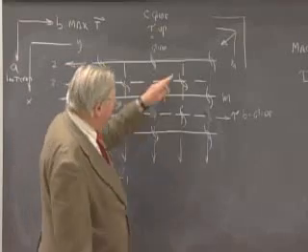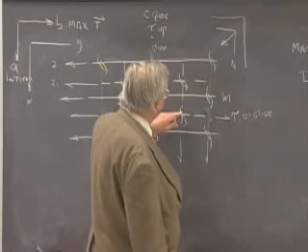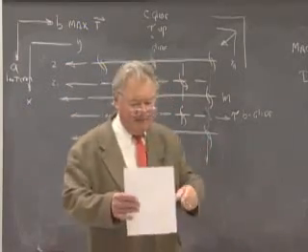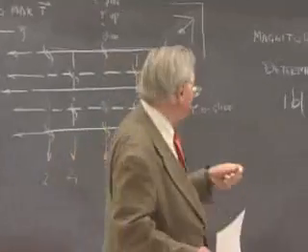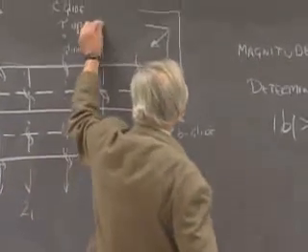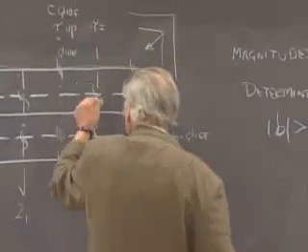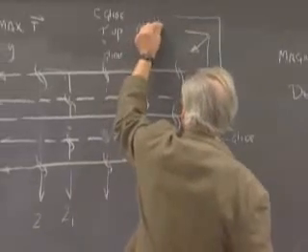And then appears a dashed dot line alongside of it. The dashed dot line is a glide plane where you're looking neither perpendicular to tau nor parallel to tau, but halfway in between. So this is a glide plane where tau is equal to 1/2 of A plus 1/2 of B.